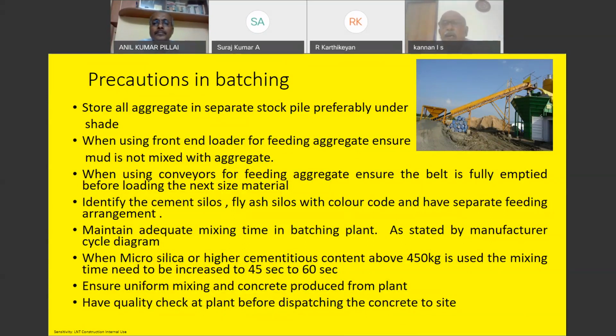Then when using a wheel loader, especially a front end loader for feeding aggregate, ensure mud is not mixed, because normally the wheel loader operator may not get friction. So what he will try to do is push. Suppose the aggregate stockpile is there, even a meter prior to that, he will start pushing everything, and he will take the mud also. So ensure some amount of material, maybe 1 or 2 feet, is left, and the wheel loader needs to be operated so that the material you are using is the right material and unwanted mud is not going inside the system.